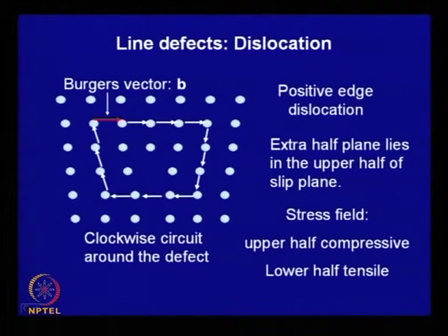The reason that we do not get it is because the crystal contains a defect called dislocation, and this is a line defect. It is a boundary between the slipped and yet to slip region. Now, let us look at the atomic structures around possible dislocations, which is shown here. So, this is a crystal, periodically arranged. See, these atoms are arranged along this line. It is a 2D crystal. This is a perfect arrangement.